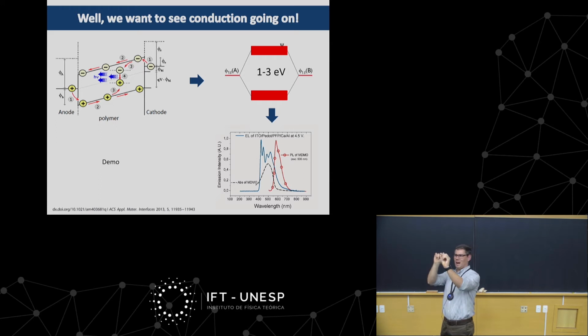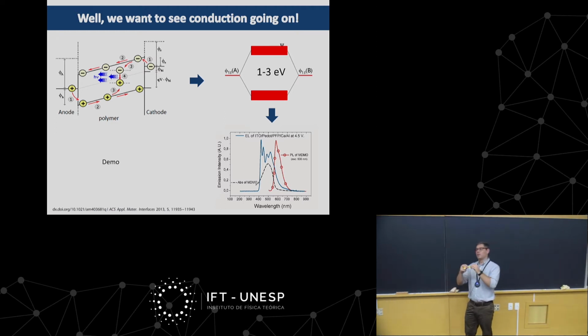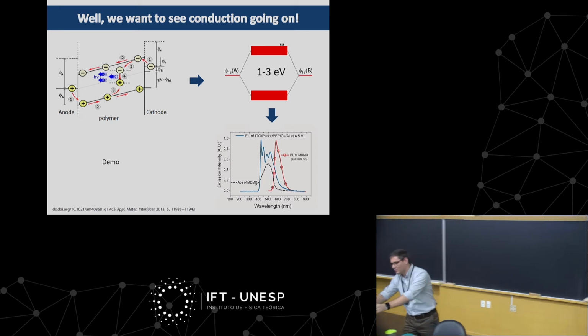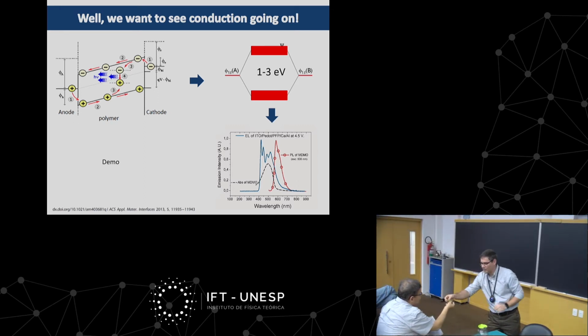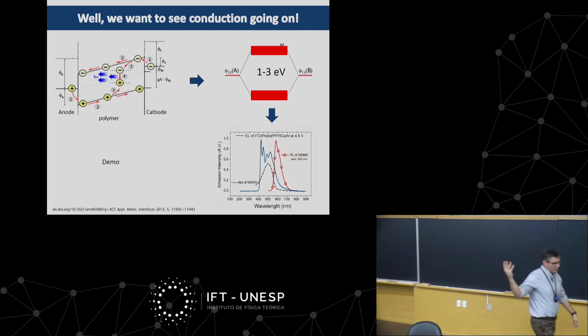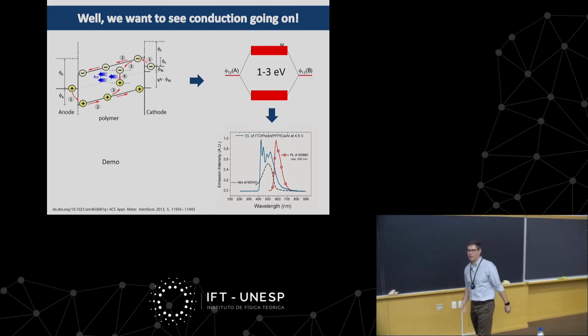And the thickness that you see on the display is basically the glass substrate, because the polymer film is about 80 nanometers. So 80 nanometers is very, very thin. So you can make very, very thin electronics. And if you want to pick, instead of a glass substrate, a flexible substrate, you can make this flexible because polymers are flexible. So I'm going to pass it along if you want to see the thickness and play a little bit. This is a yellow material, so it shines in yellow, but we have all types of colors.